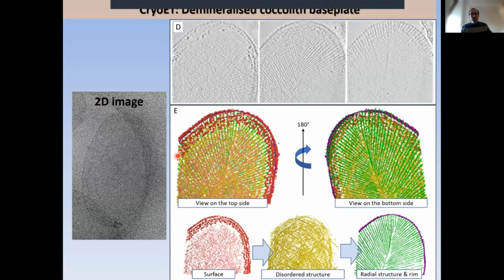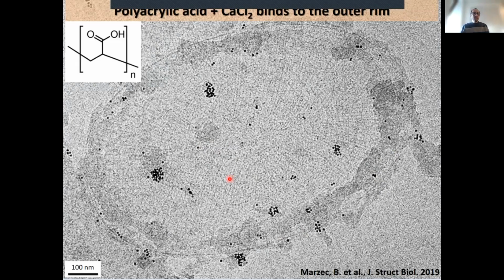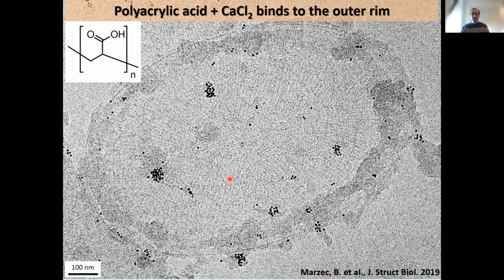What is interesting here, though, is that the rim of the base plate in red, which is where the crystals nucleate and grow, is morphologically different from what is inside. So that is already showing that there is a difference in morphology. Now, we did some experiments using polymers as mimics to the acidic polysaccharides, and we could see, this is another